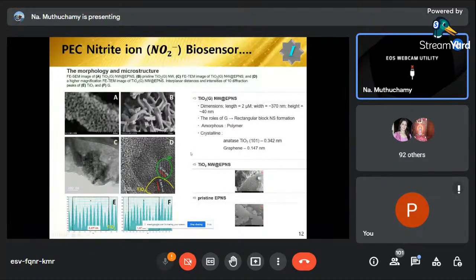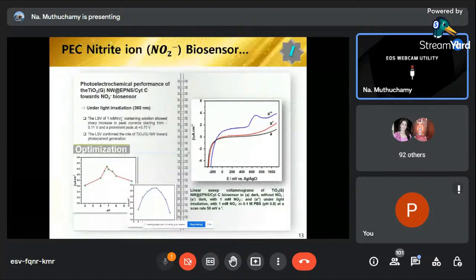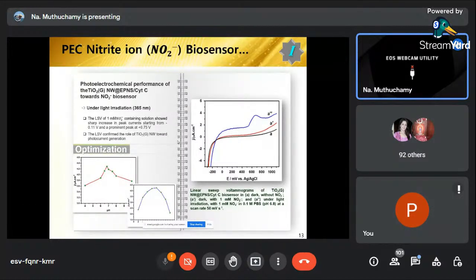And when we go to the application part, TiO2 is a semiconductor, graphene is a conducting material, and the functionalized polymer plays a main role in binding the cytochrome. Cytochrome acts as an enzyme, and it reacts with the nitrite ion. Here you can see we optimized the pH conditions and the loading of the catalyst. We also confirmed the nitrite ion sensing potential through the linear sweep voltammetry technique.